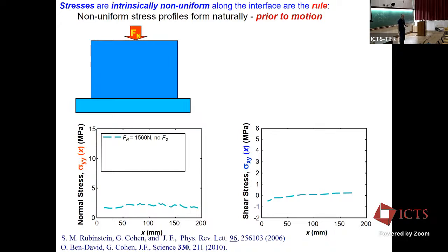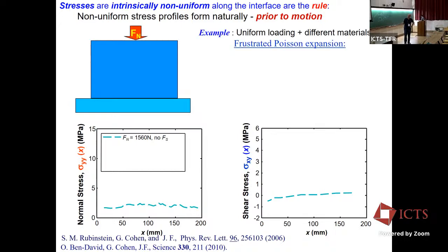As we take a perfectly homogeneous normal force, and these blocks that we made, that I'm talking about, aren't the kind of blocks that you buy from your store and then just sand down or something like that. In order to create a very good interface here, these are diamond machined to optical flatness. And then they're roughened by scientific sandpaper. Why is that? Because if this interface was rough, even on a micron scale, or wavy on a micron scale, we'd only have one or two points of contact. And I want an ensemble of contact points. And that's why we went to some effort to make these two mate perfectly. Okay, anyway, I'm starting to push down, and this is the normal force, and take a look at what happens.